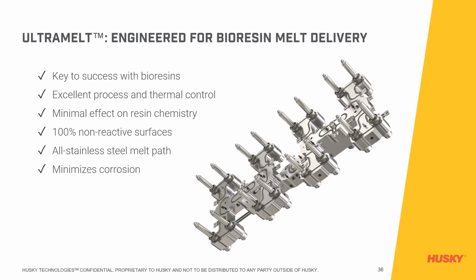Our UltraMelt hot runner is the key component of that. UltraMelt is engineered for applications requiring excellent process and thermal control with minimal effects on the resin chemistry. This specific hot runner features 100% non-reactive surfaces and all-stainless steel components to preserve the sensitive chemistry of the bioresin, minimizing corrosion and other challenges. With the UltraMelt, the melt path is protected. So from the sprue bushing to the manifold bushing, the valve stem, the nozzle housing, the nozzle tip. As I said, every component that touches plastic is either stainless steel or a non-reactive coating to protect that steel and that hot runner to last you a very long time.